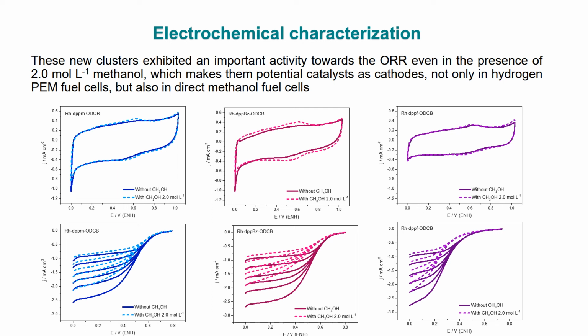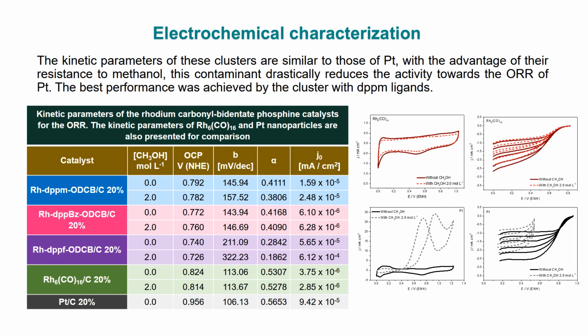methanol fuel cells. The kinetic parameters of these clusters are similar to those of platinum, with the advantage of their resistance to methanol. This contaminant drastically reduces the activity towards the oxygen reduction reaction of platinum. The best performance was achieved by the cluster with methylenebis(diphenylphosphine) ligands.